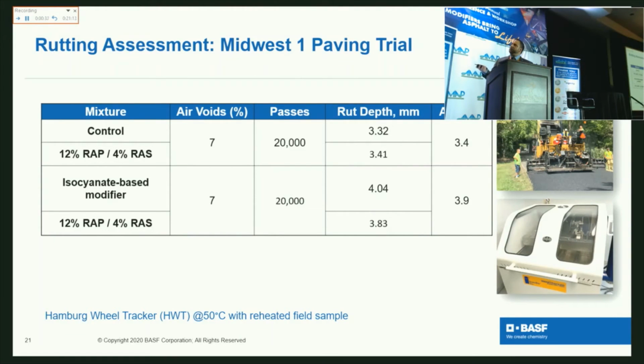Our blend was a 3.9 on the deformation, on the rutting. Statistically, that's essentially the same. This mix that they used is the one that they used for the DOT grade mix. There was essentially no improving this mix.